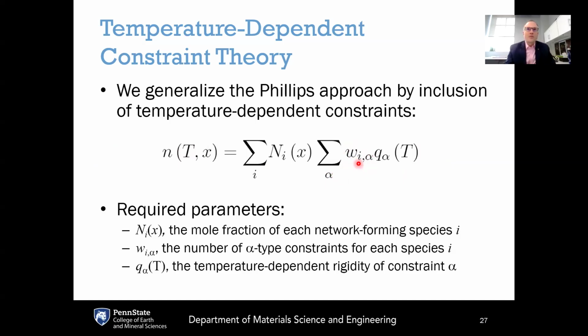So say the number of radial constraints or the number of angular constraints. That's W_i^alpha. So for species i in constraint type alpha, that W gives you the number of constraints. And then a temperature-dependent constraint function q_alpha, which is a function of T.